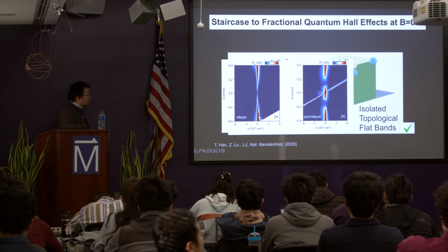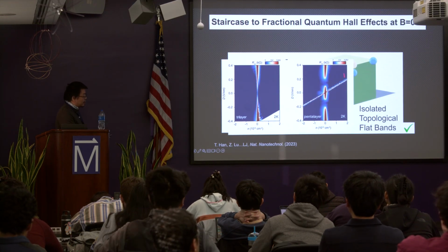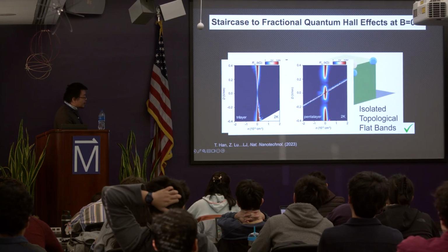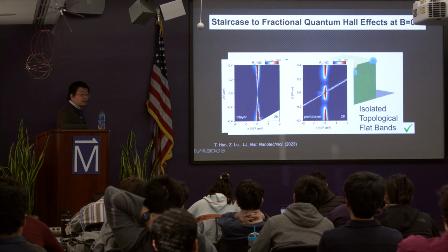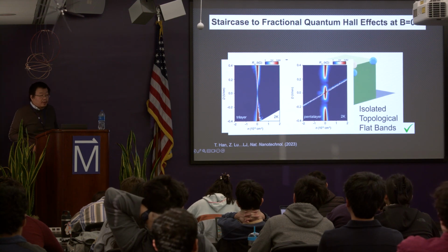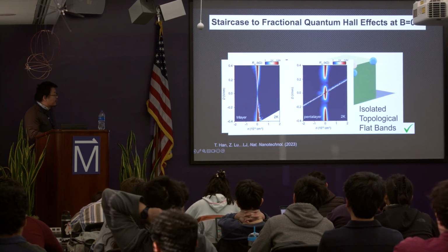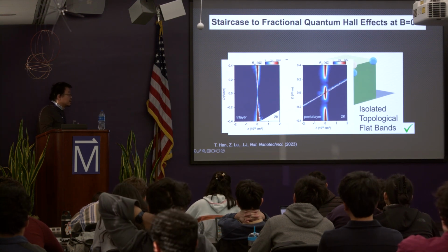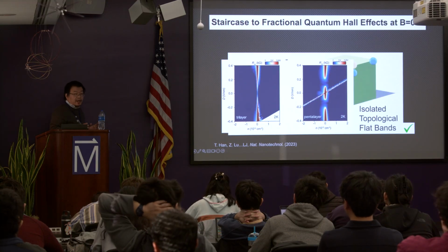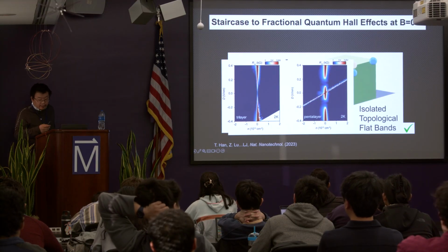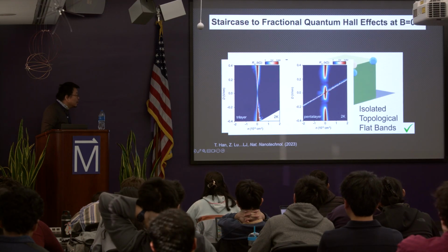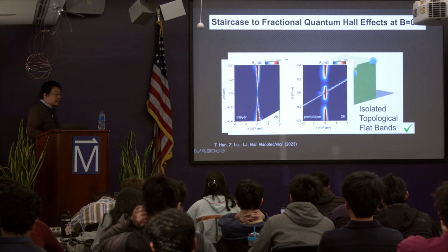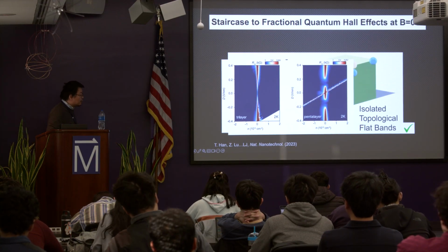But rather than metal, you can see this is a pentalayer, which is 5-layer. So at zero n and zero electric field, it's actually a very good insulator. That means that here, you already have a gap opening by the interaction that's driven by the flat bands. So yeah, you have some flat band effect. And how about the topology?